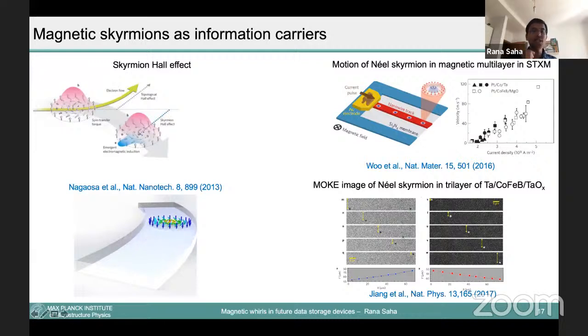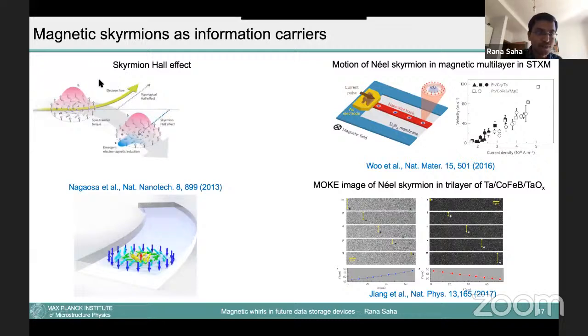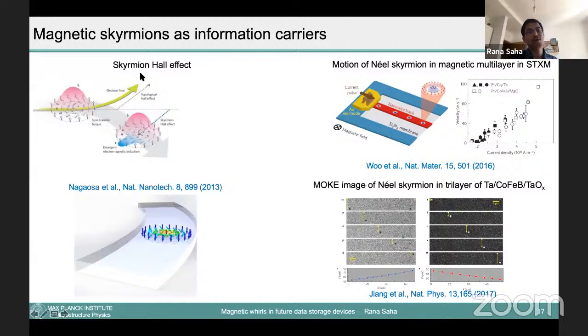But when the electron goes in the transverse direction, it also applies the opposite force. So when you apply a force, the skyrmion should move in a straight line, the racetrack as I mentioned, but instead of moving in a straight line, it moves sideways. When it moves sideways, what happens? Instead of going straight, it can hit the wall and you can lose data, because each skyrmion stores data as either 1 or 0. You can understand this with this famous